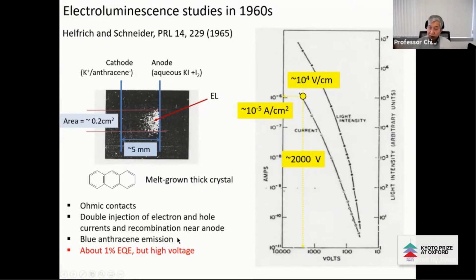The efficiency is roughly about 1%. But the key issue here is that the voltage required to drive this device is very high. It's about 2,000 volts. So even though the efficiency is quite remarkable, in practice, it's not very useful as a light emitting device.